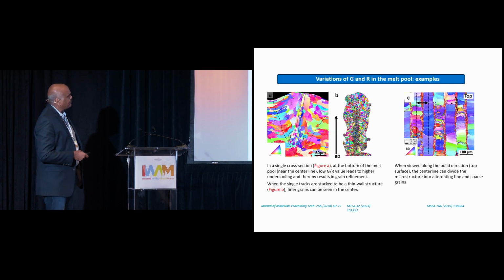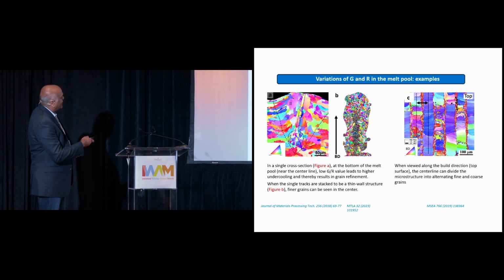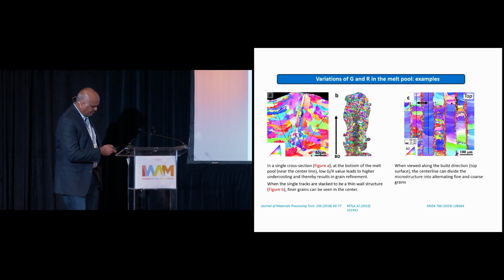The growth rate and thermal conductivity directions can affect these things. For example, here you see very fine grains - this is a single melt, single track. But if you build on this, you can see the microstructure, the grain structure, is very fine, whereas on the outside it's much coarser. If you build several of these layers, you see very complicated microstructures coming into play.